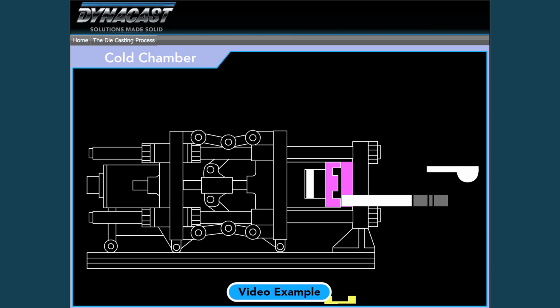Molten aluminum would be around 1240 degrees Fahrenheit. It gets scooped up in a ladle, gets poured into what they call a shot sleeve, and then gets injected into the die. And you can see a video here of the actual, that's the ladle, poured into the shot sleeve, gets injected, the casting is made. The robotic arm comes in, extracts the casting out, a die lube spray mist comes down, sprays mold release for the next shot, and it continues.